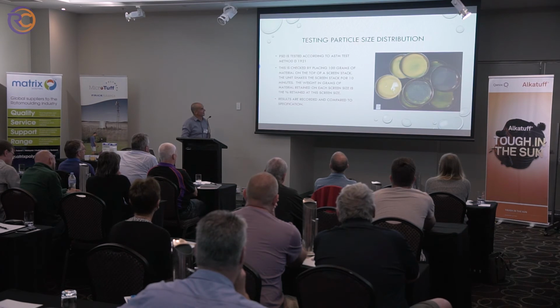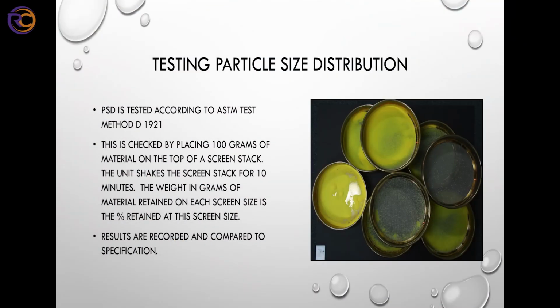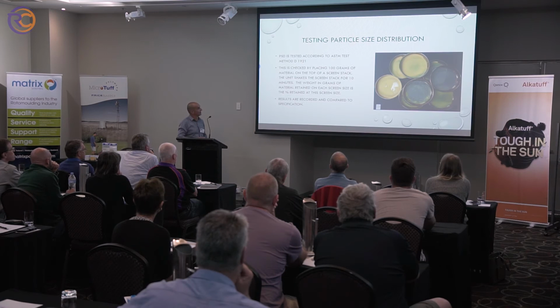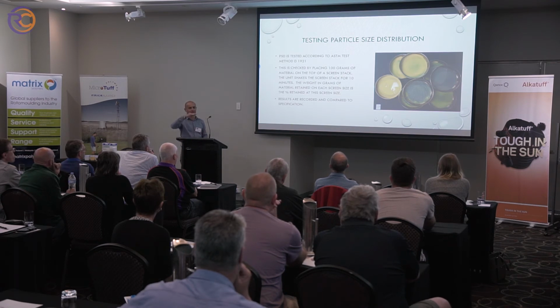So, the testing of the particle size distribution. The PSD, as some people refer to it, is tested to ASTM test method D1921. And this is checked by placing 100 grams into a stack of sieves like that. And these sieves are shaken for 10 minutes, and each sieve represents a different particle size or mesh size.